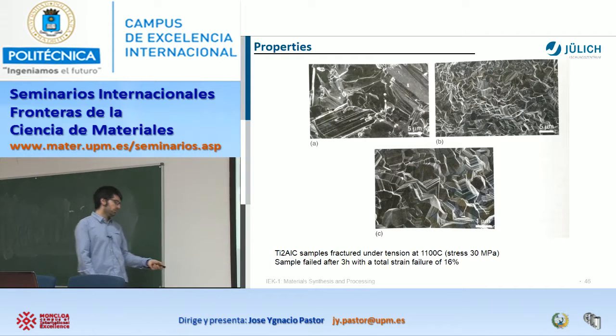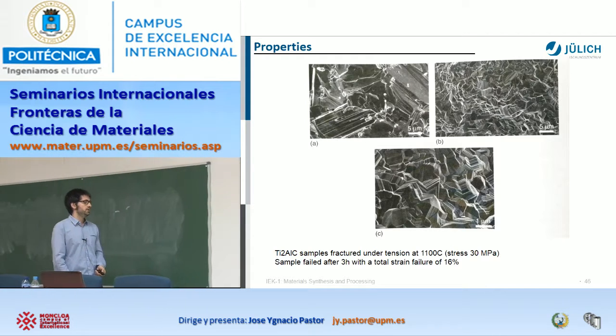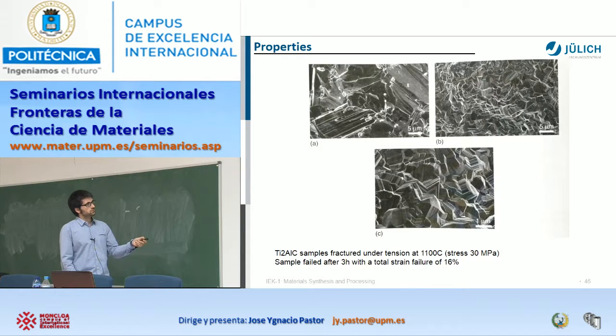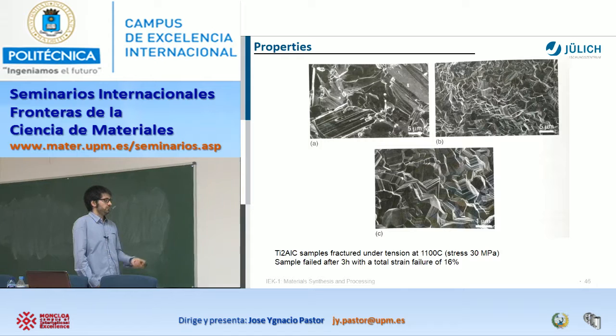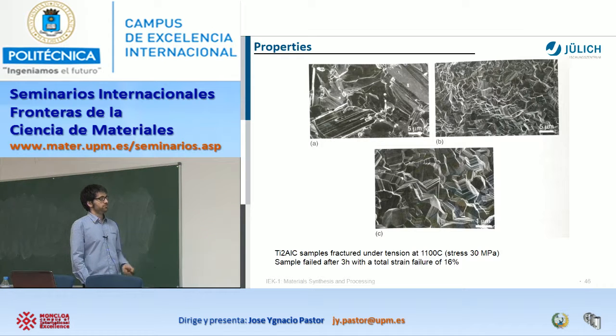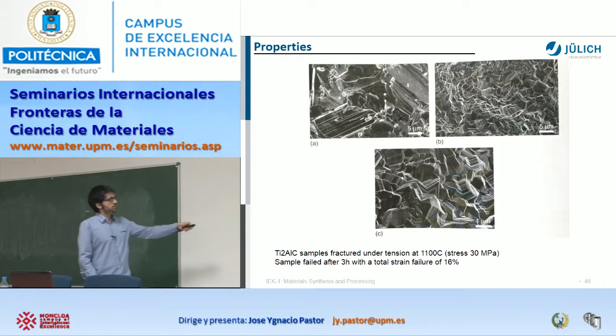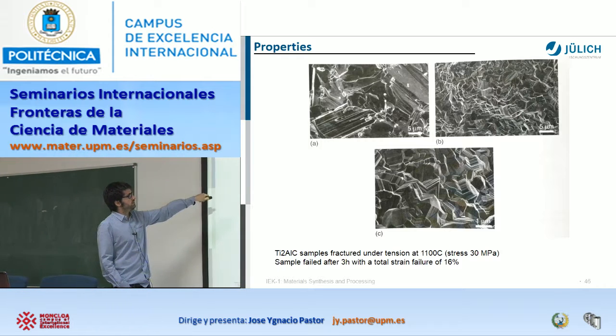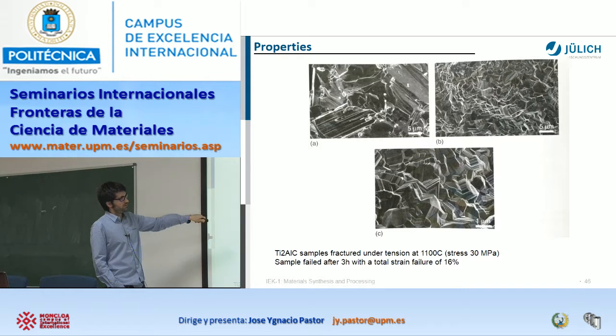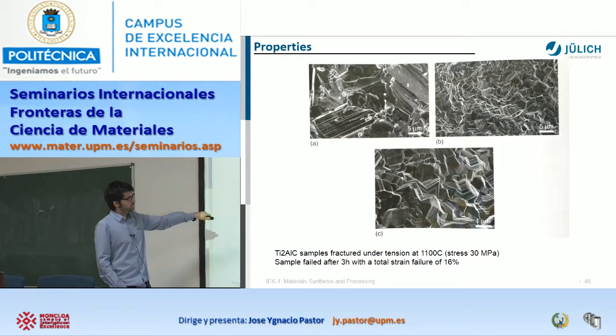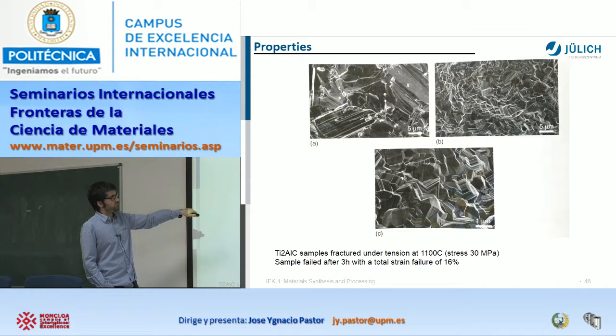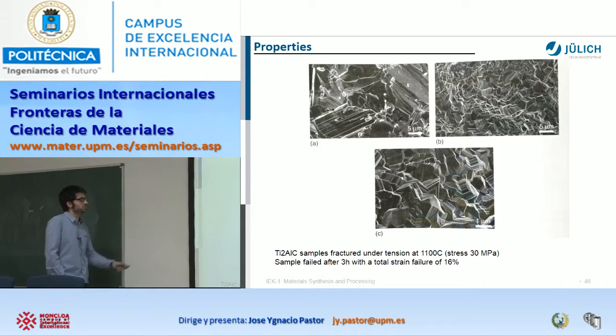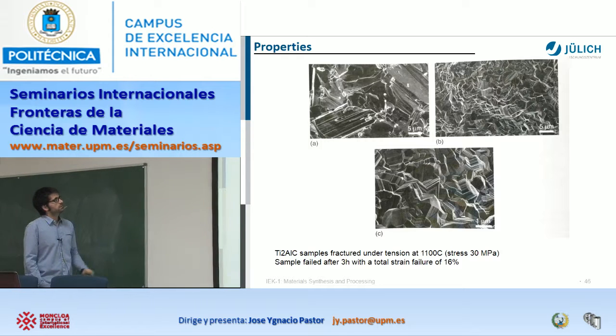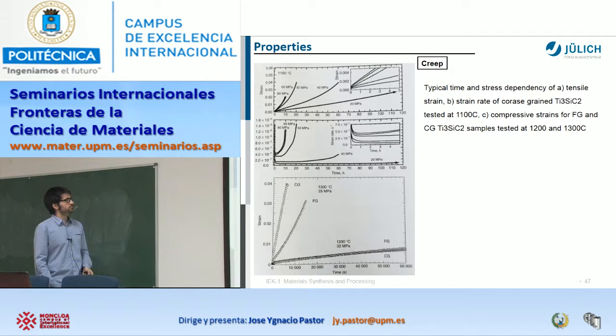This is the other most studied phase, this titanium aluminum carbide, showing the fracture surfaces under tension at 1100 degrees. Okay, and this sample at the end fails at 3 hours. But the strain to failure is 16, that is quite high. And here you can see this layer structure of the material that is clear, or even this picture, I really like it, how the grains are bending to obtain this. It is totally impossible in other ceramics. Okay, and this is due to this layer structure.